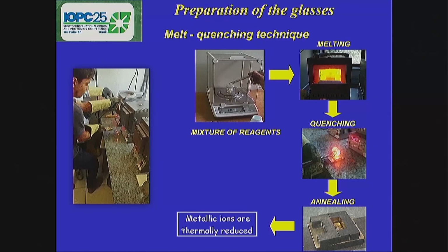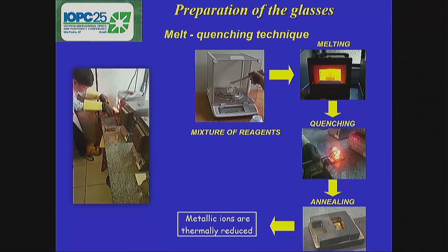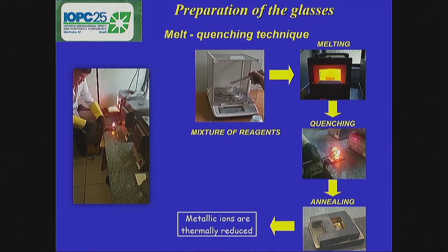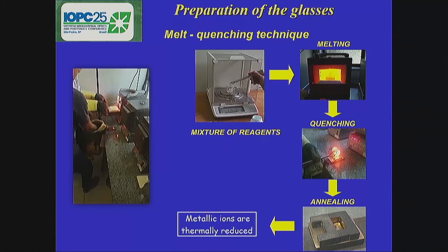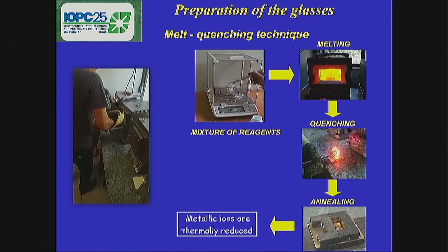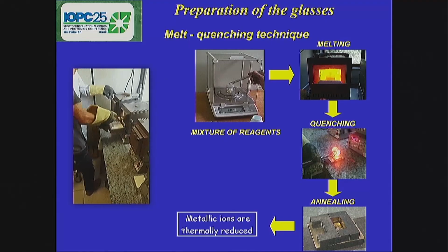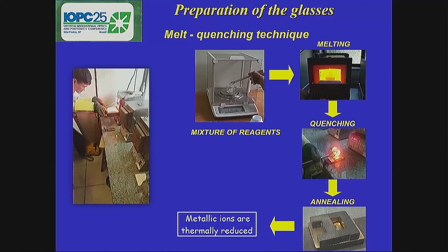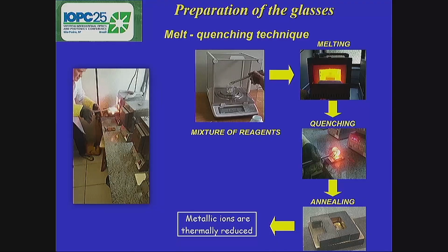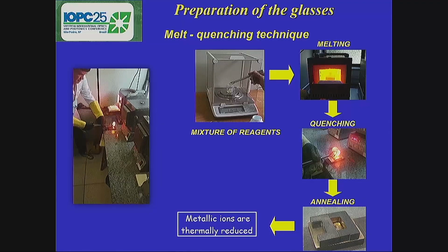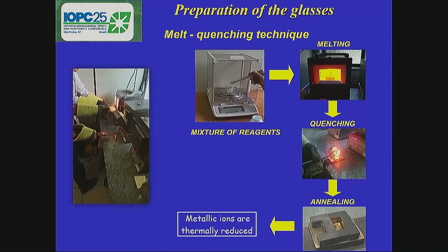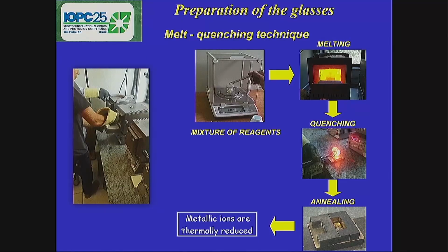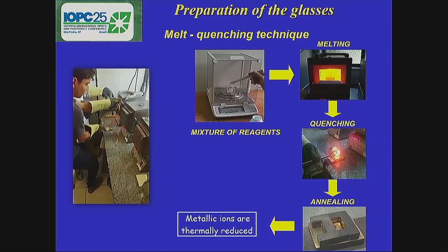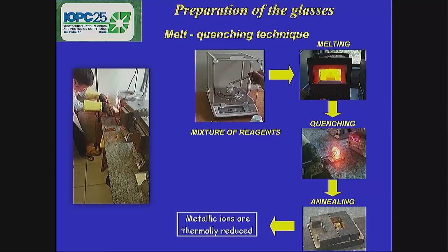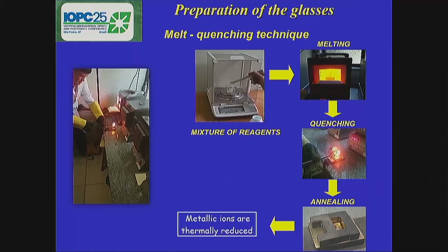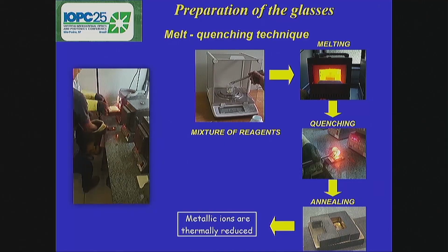And here I show the steps used for the preparation of the glasses, the well-known melt quenching technique. For those that are used to glasses, it is a familiar technique, a very simple one, in which we first have the mixture of the reagents, followed by the quenching in a preheated brass mold, and the final step is the annealing. The annealing is performed to reduce the internal stress, which is an important step because it lets the sample become less fragile, mainly during polishing.